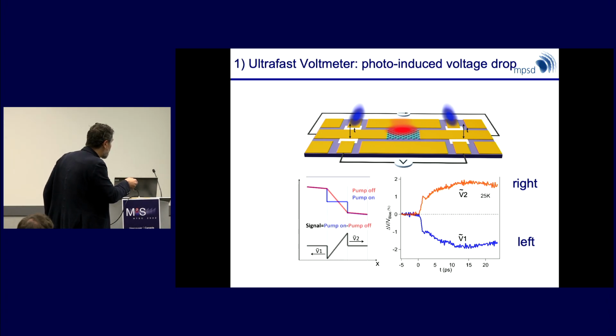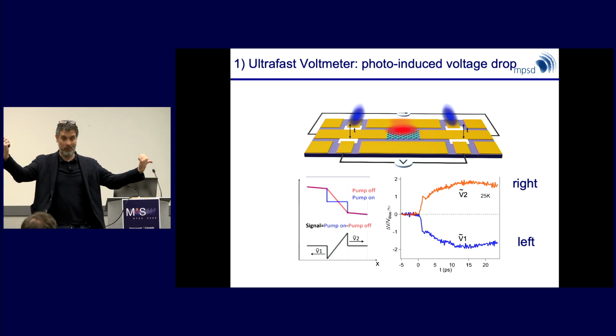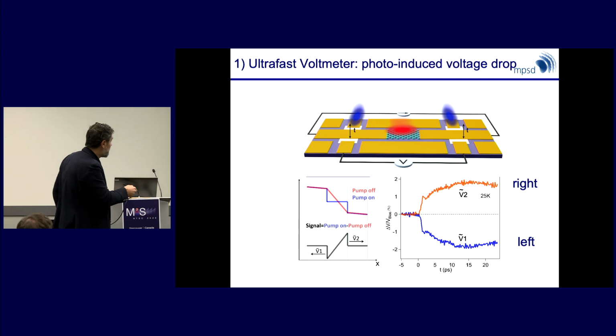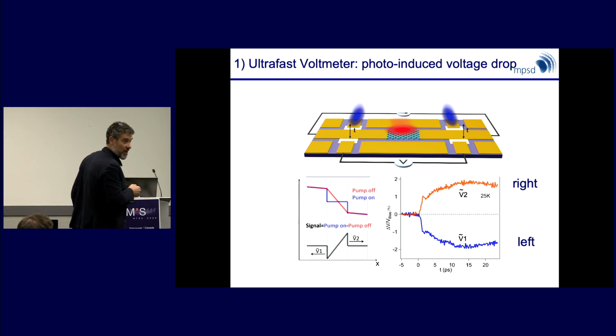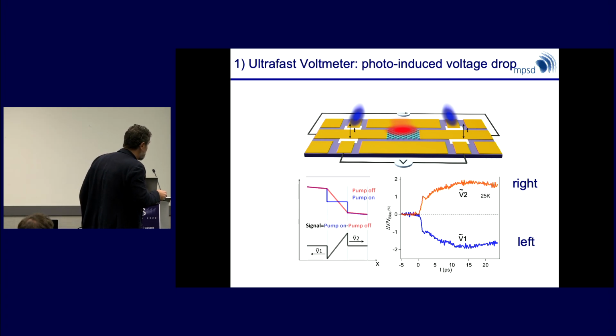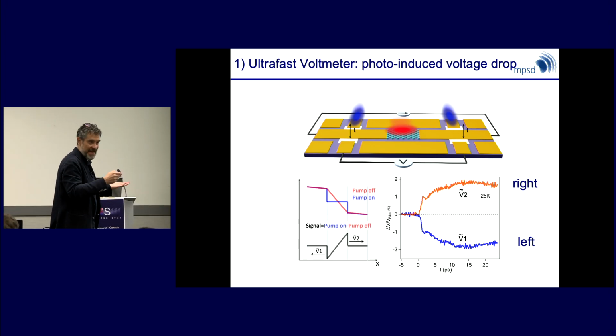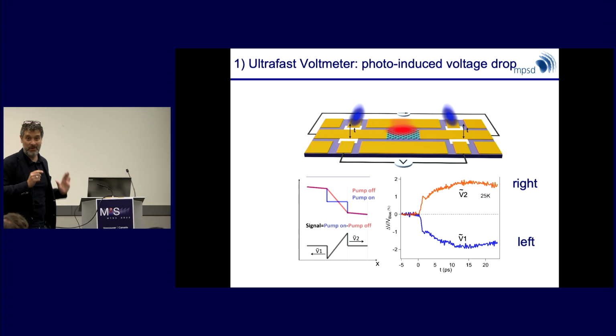I get a voltage drop here only at the interface, and then there are two terahertz pulses that propagate, one to the right, one to the left. If I measure this contact or this contact, there's a DC current here that keeps the voltage drop onto these strip lines. So the voltage should go higher to the right and lower to the left, within a time scale that has to do with this transition. This is broadly consistent with what we expect.